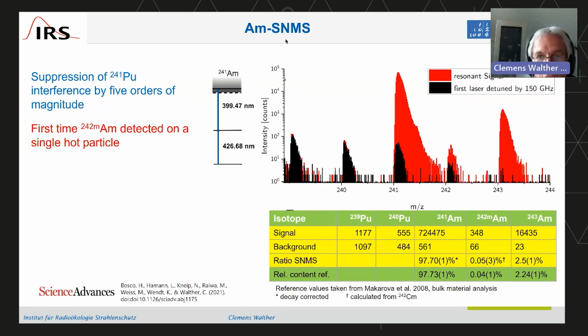After suppressing the plutonium against uranium, the next thing we did was suppressing the plutonium against the americium. We have the 241 peak, and again we have plutonium and americium on the same mass and need to detect that. But here I want to focus your attention on the 242 peak, because in the americium you produce as major isotope americium-241, which is additionally produced by the decay of plutonium-241. And you produce americium-243 from the uranium-238 and a lot of neutron absorption. But there's also a tiny peak of americium-242, the long-lived americium-242m. And we were quite proud to firstly detect that in a single hot particle with this technique.